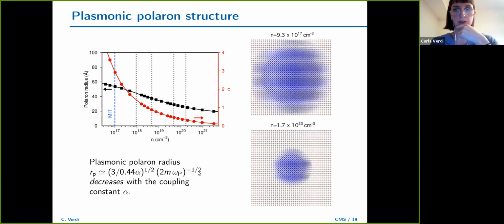This is the Feynman model. The Feynman model is actually the most exact solution of the polaron problem, but it's the ideal polaron problem. So it solves the Hamiltonian where you have simply a single electron interacting with a single boson. And this is the plasmonic polaron radius. It depends inversely on the so-called alpha parameter, which is related to the electron-boson coupling strength. And it also depends on the boson frequency. So here, the plasmon frequency.